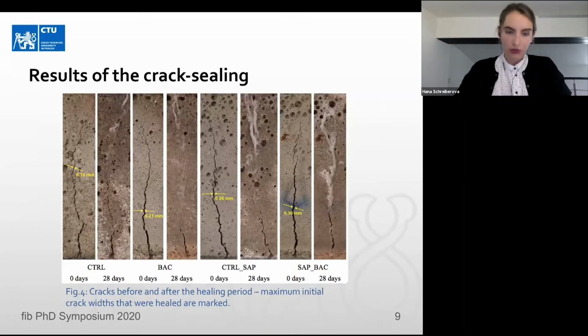In this figure, figure 4, you can see the images of the chosen cracks before and after the healing process. And it is apparent that in all of the cases some level of crack sealing, that's the white crystalline precipitates, took place. In these pictures, the yellow arrows mark the maximum crack width that was healed in the 28 days healing period. This value was ultimately chosen for the comparison between the prepared mixes.